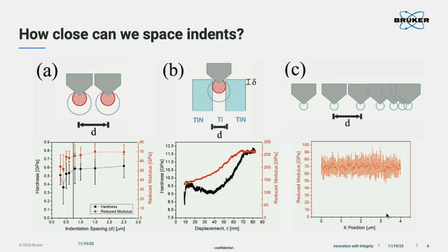So if you look at this, you can see the hardness and the modulus influence is different. For this, I think the modulus is already mixed with two materials. For hardness, it's still in the one zone. So of course, the data will be more uncertain because we don't know where the elastic and the plastic zone will exceed the boundary. So we also need to consider what the phase size is. Then we decide the pitch for the indentation.